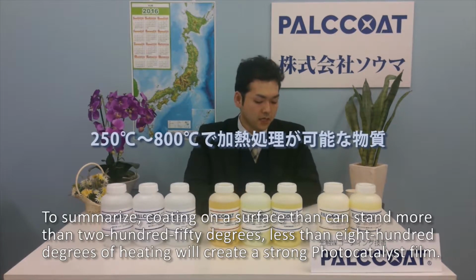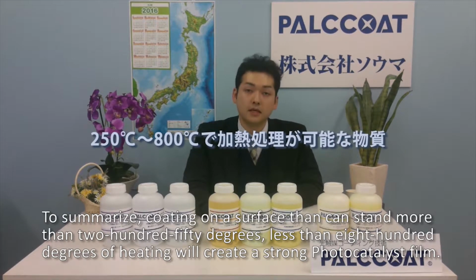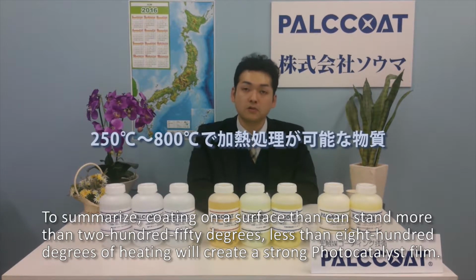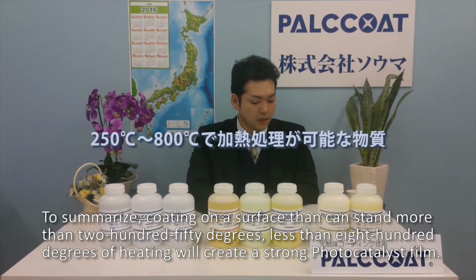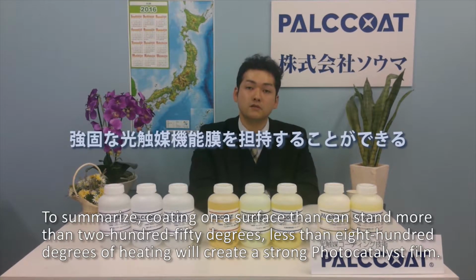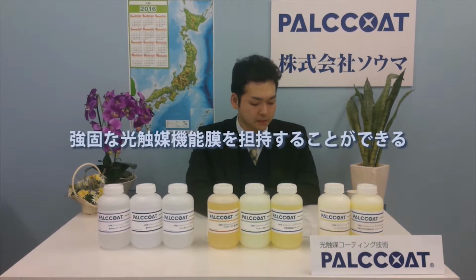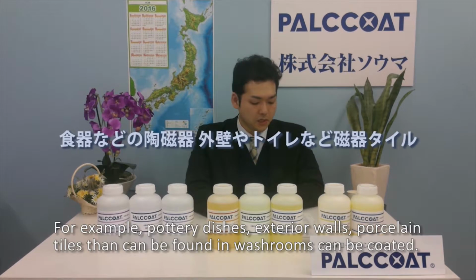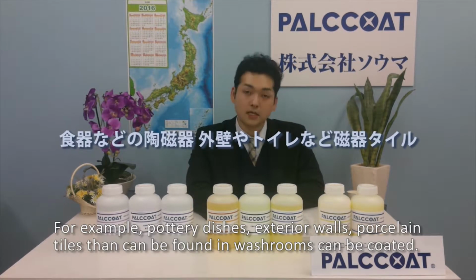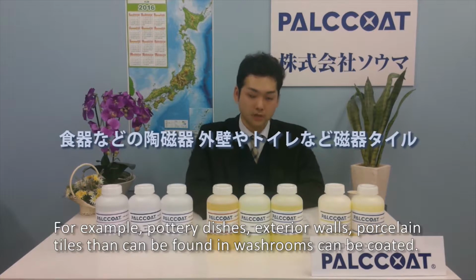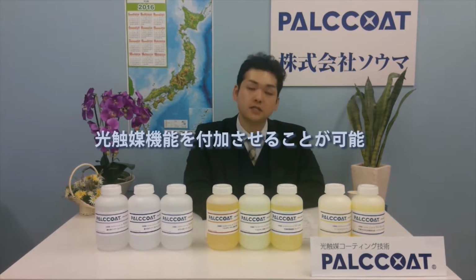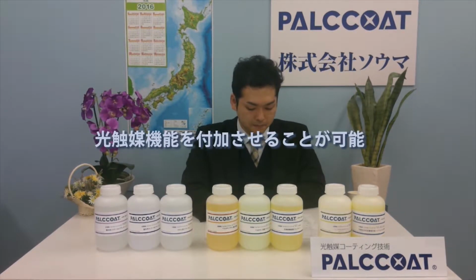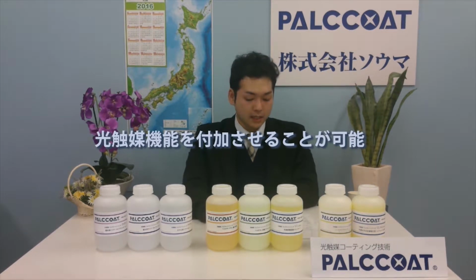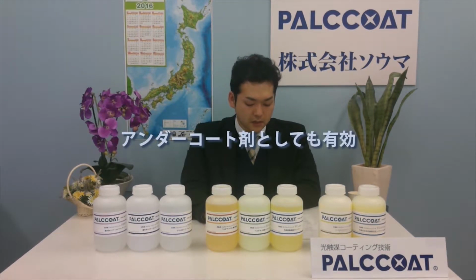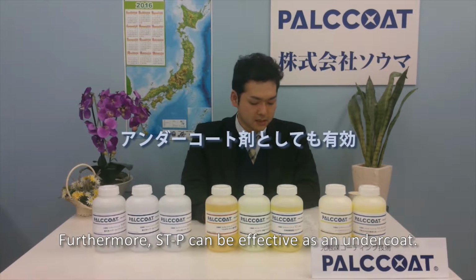To summarize, a coating on the surface that can stand more than 250 degrees and less than 800 degrees of heating will create a strong photocatalyst film. For example, pottery dishes, exterior walls, and porcelain tiles such as those found in washrooms can be coated. Furthermore, STP can be effective as an undercoat.